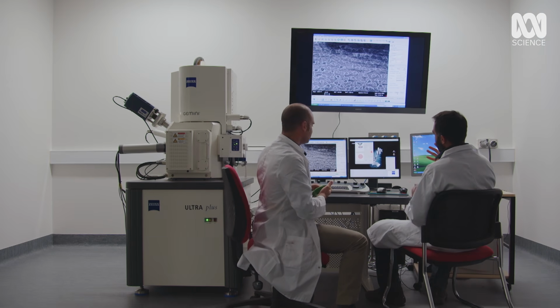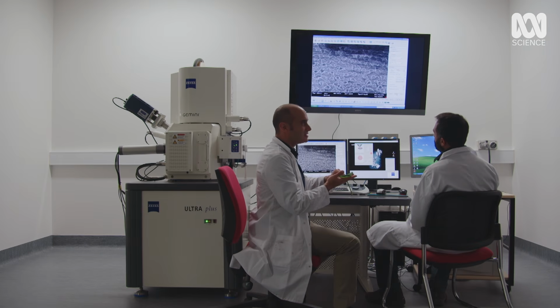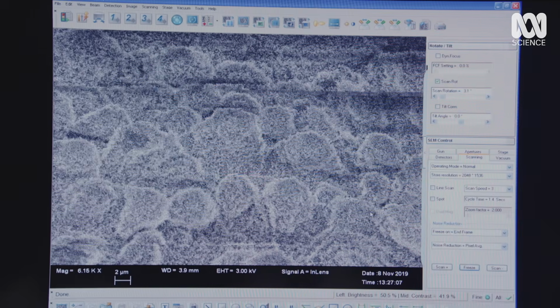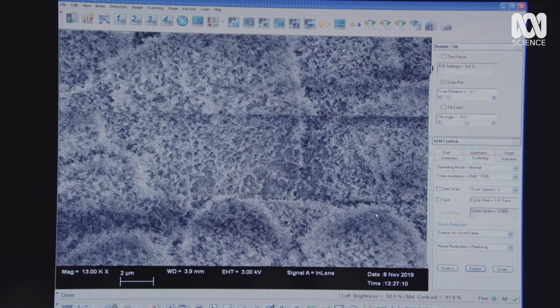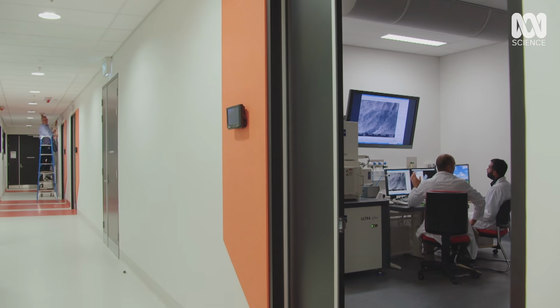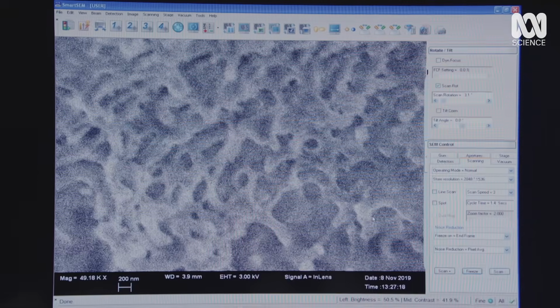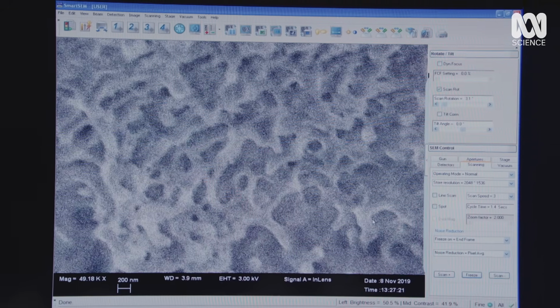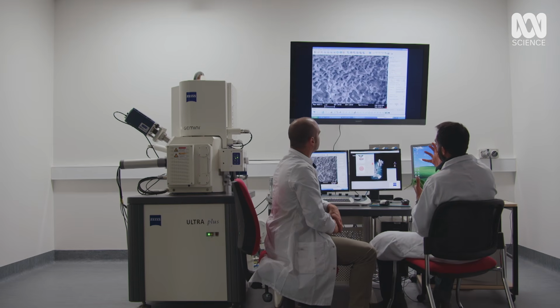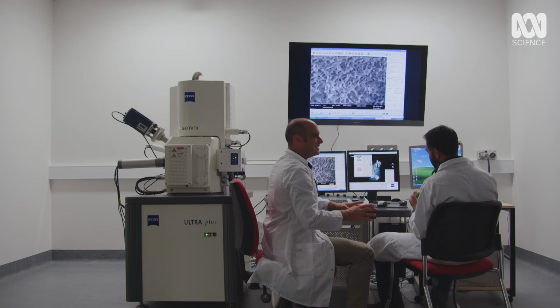So what we're looking at here is the nanostructure of the lotus leaf. Exactly. We shoot beams of electrons to surfaces, and in this case, we look at what comes back. So the scale bar here is 200 nanometers. Yes. It's smaller than the wavelength of UV light. Significantly smaller, and the particles actually are around 5 to 10 nanometers. These tiny bridge-like structures create air pockets, and it's these air pockets that prevent the water from touching the lotus leaf's surface. So you're trying to replicate this kind of surface with your materials? Exactly. Now, replicating what nature does is not always easy, as you may imagine.